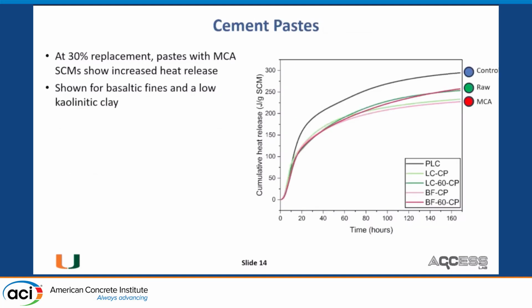Okay, can we do anything about cement pastes and mortars? We did limited work here, but essentially what we see again is a clear effect of the amorphization that we generate reactive SCMs. So at 30% replacement, the control is up there. I switched those out, I'm sorry, I don't know why I did that, but anyway. These are switched out, the MCAs are the other way around, but the MCAs show substantially higher heat release than the raw materials, but at the same time lower than that of the control materials.